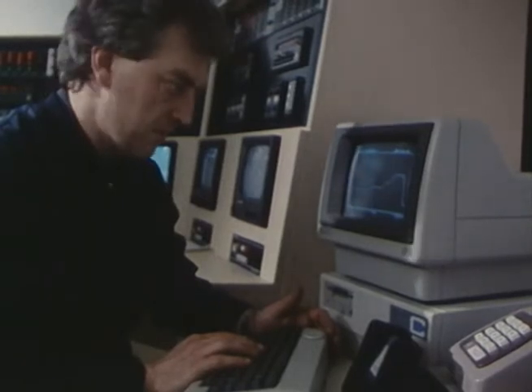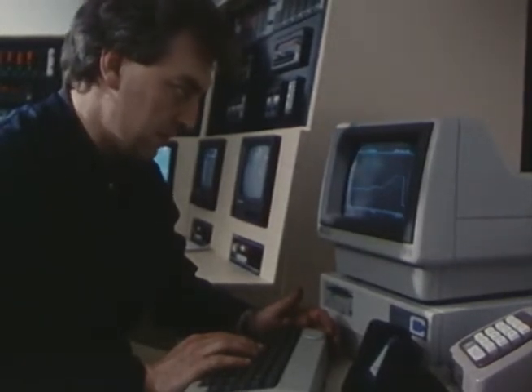When the cycle is complete, the spar is inspected for wall thickness and structurally examined by radiography. X-ray examination of composite materials is a new science, almost a new world, like TV pictures from Mars. Here in this early trial specimen, we have included a tiny particle of metal which glitters in the X-rays like a cut diamond. The dark, irregular shadows along the top of this trial spar reveal a wrinkled nose moulding. All spars are scrutinized in this way, and thus we have a high confidence in our quality standards.